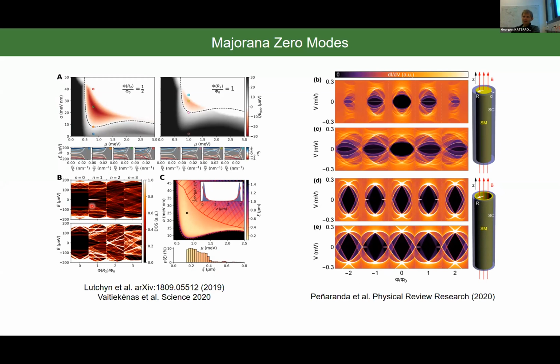And by calculating the local density of states, a zero bias peak is appearing in the first lobe, while in the bulk of the wire, you don't see anything. Later on, Fernando Penaranda did numerical simulations of the local density of states by investigating a bit further the geometry also of the semiconductor core, whether the indium arsenide nanowire is a full cylinder or a hollow cylinder. And they found as well that under appropriate conditions, you can end up with Majorana zero modes in the first